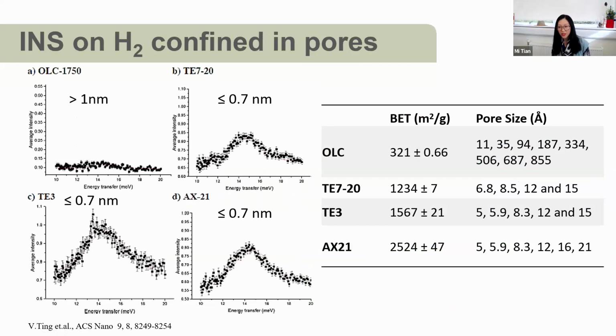There's an obvious question: do all the porous materials work on this principle? Actually, no. We tested different materials, and we realized only the porous materials with very tiny pores, less than 1 nanometer, can solidify hydrogen at this condition. For example, with this onion-like carbon with a pore size larger than 1 nanometer, we don't see this solid hydrogen peak. Which means when the pores are too large to accommodate solid state hydrogen, it's not very useful in this case.